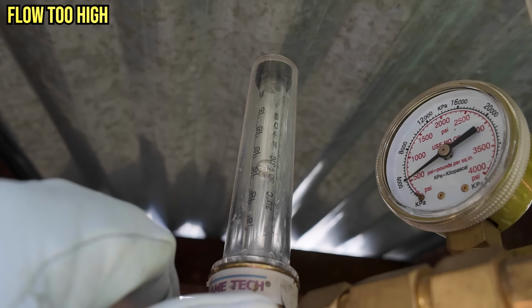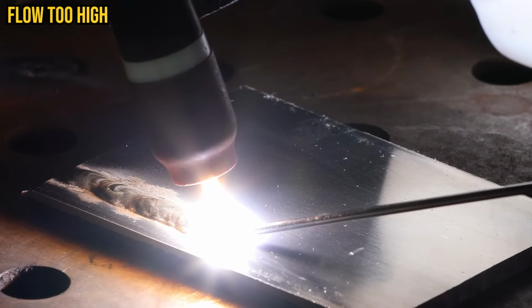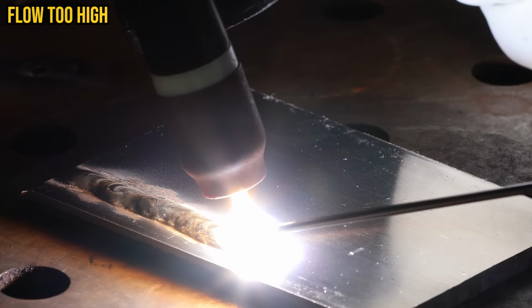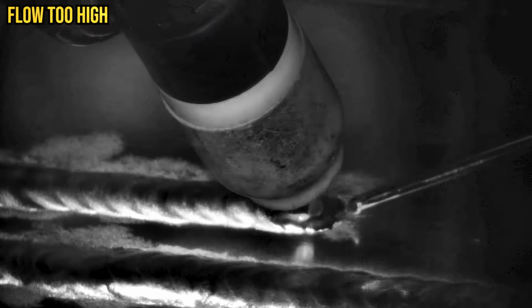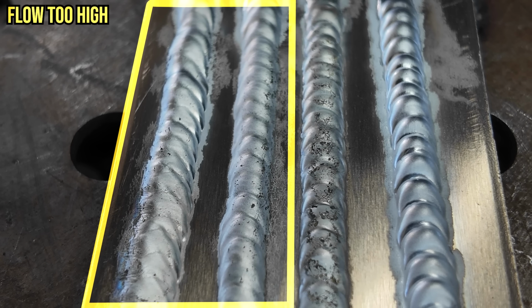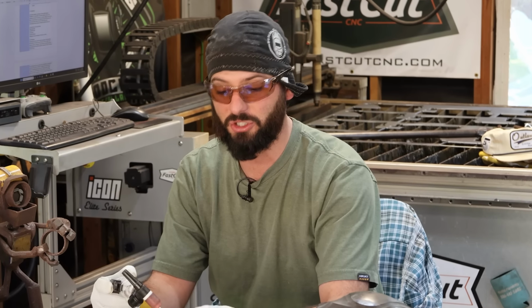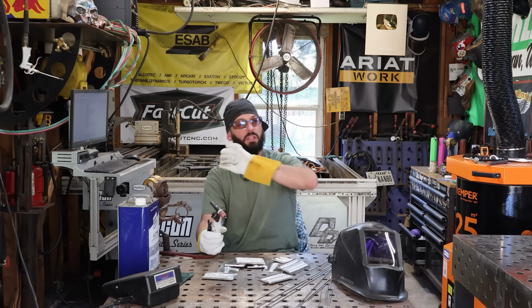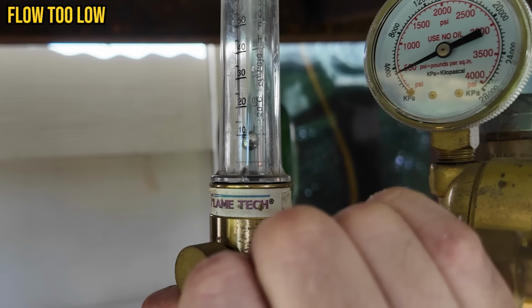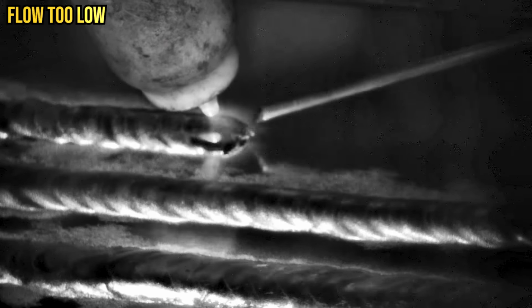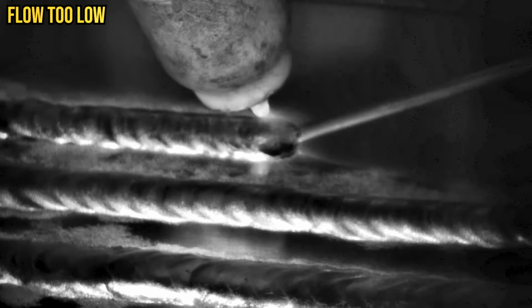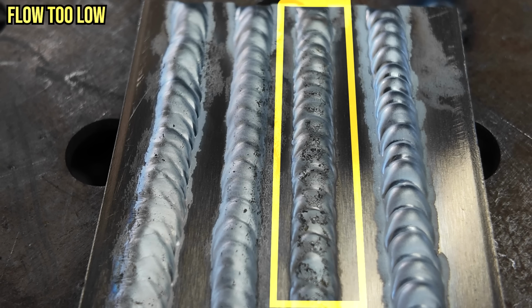If I go ahead and try to turn the argon way up like I might if I'm trying to weld really pretty colors with stainless steel, there's so much turbulence on this soft weld, and I'm still seeing oxides getting pulled in from all that back pressure that we're seeing from the torch being so narrow, and it's just so aggressive on that weld. Now, if you turn things a lot lower, closer to like 10 or 12, maybe 13, I feel like you can still get away with welding here, but God forbid there's a little draft or a little breeze or your torch changes an angle, still not enough shielding gas to really get us a nice clean weld all the way across. It's probably the dirtiest one of them all.